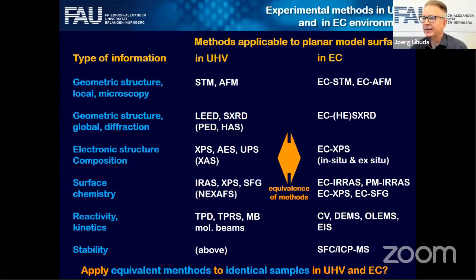You can also be lucky. For the cobalt oxide, for instance, we have the advantage that we're working under alkaline conditions. And under these conditions, these carbonic acids don't adsorb strongly. So under these conditions, you don't have to deal with this problem so much. The message is really, of course, you should try as hard as possible.